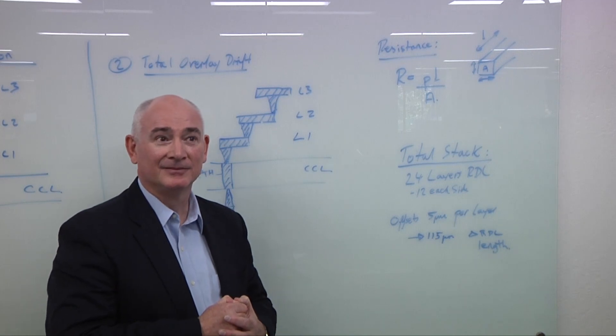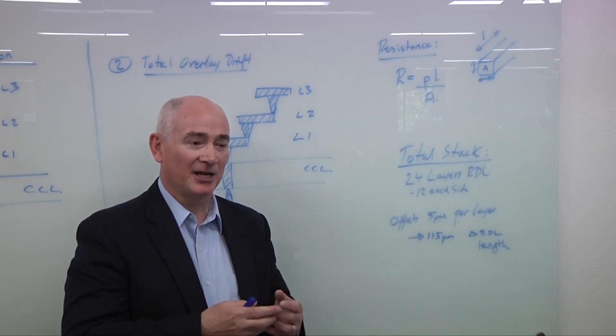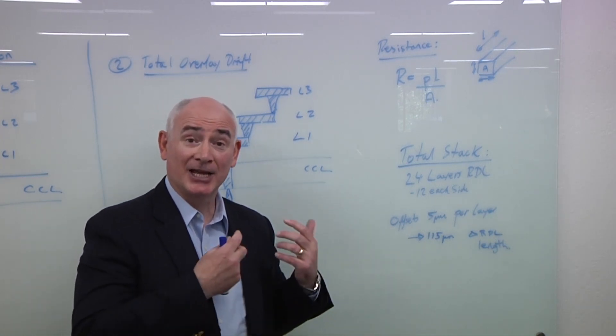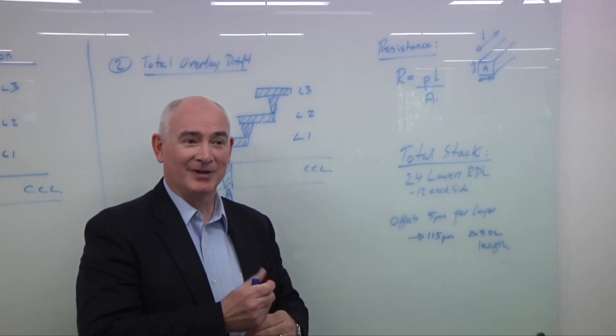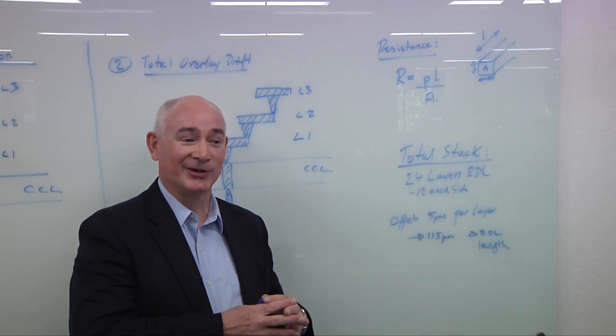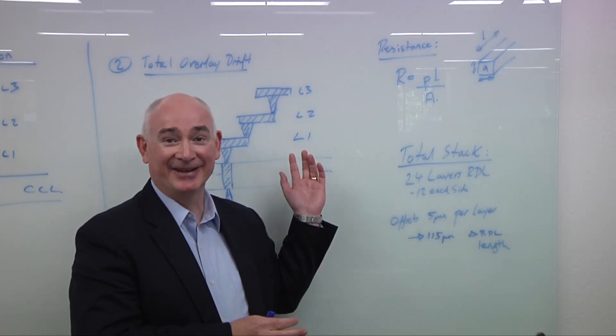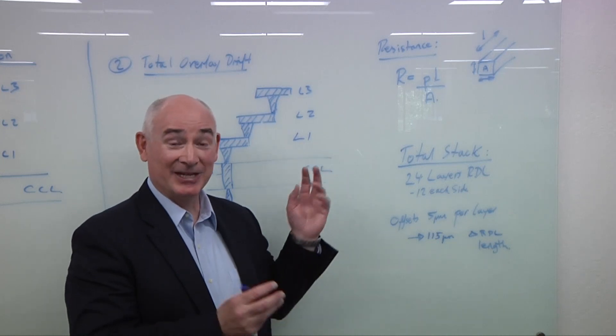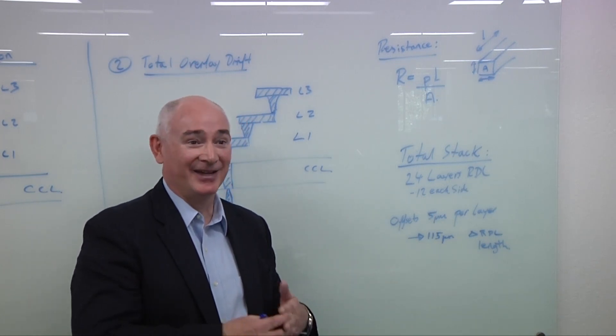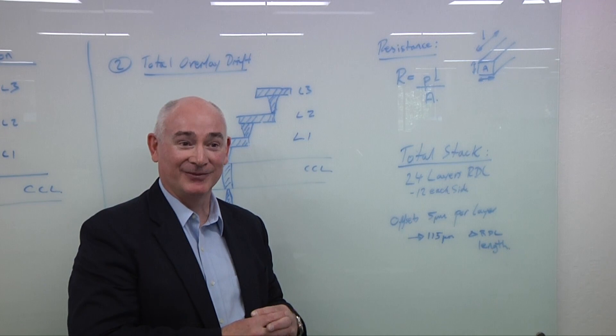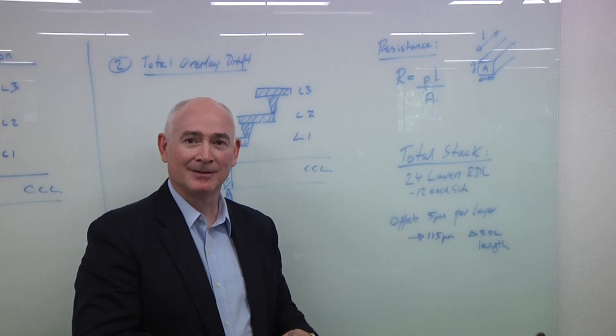Are the RDL materials changing as well? Well, in essence, mostly the same, but some of the way they're created and employed will be different. So, for instance, you see electroless copper being used for the CCL. You move into glass, you'll be doing electroplating copper. And also, the seed material, you know, that will be slightly different. So it's just adapting to the resolution and the node. I mean, this came from PCB back in the old days, 50 microns and above. We took PCB knowledge and materials and tried to push them into this space. And, of course, they're running out of steam. And there's a tipping point. And I think two microns especially, that's where it's going to have to happen.